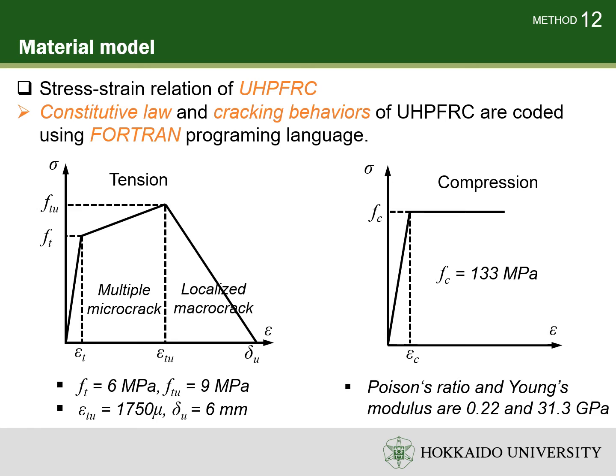The maximum tensile strain for the strain hardening domain is 1750 micro. With this state, the multiple microcracks start to form and propagate stably. Beyond the ultimate tensile strain, the macrocrack initiates at the strain softening domain, and UHPFRC finally fails at the end of this phase, with the ultimate crack width equal to 6 mm chosen by half of fiber length.